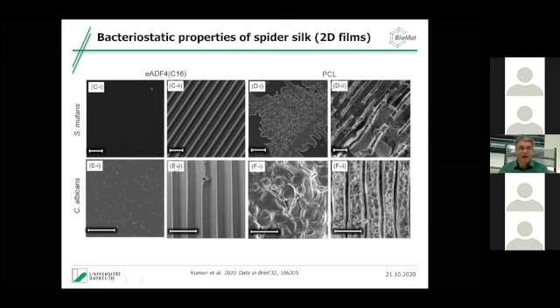So we could already show that on flat surfaces, spider silk works very well, and this, of course, accompanies what I've shown you before with the fibroblast studies and with the silk coating of the breast implants. Nothing likes to stick to it.